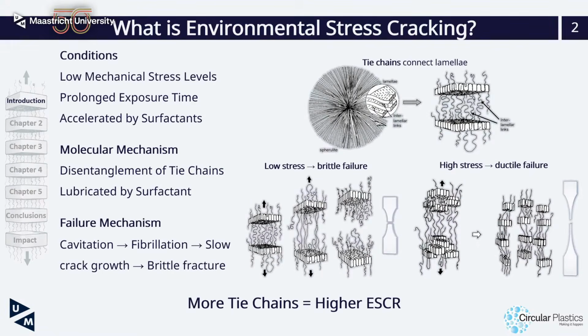To understand environmental stress cracking, it helps to first look at the structure of HDPE itself. HDPE is a semi-crystalline polymer. It contains crystalline units called lamellae. And between those lamellae, we have amorphous chains. Some of these amorphous chains that can connect at least two lamellae to each other are called tie chains. When a high stress is applied, the lamellae break and the material can stretch significantly before failure. That is called ductile failure.